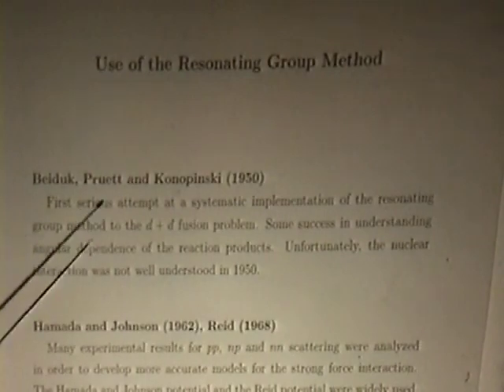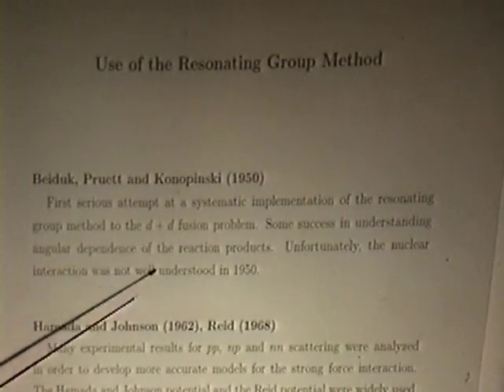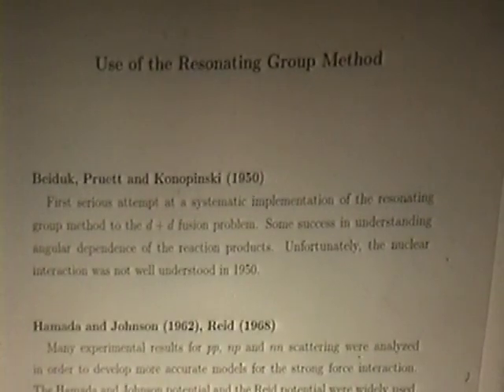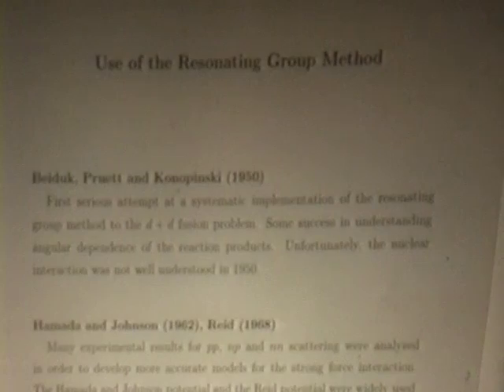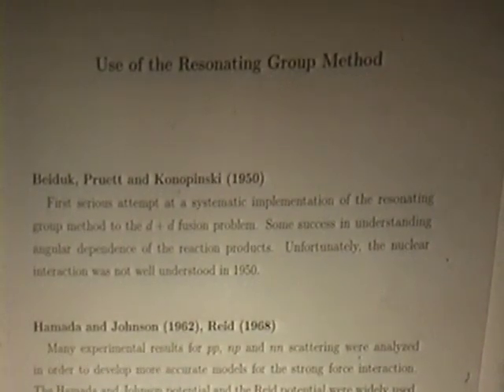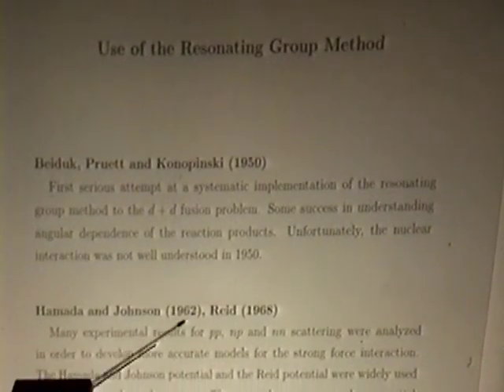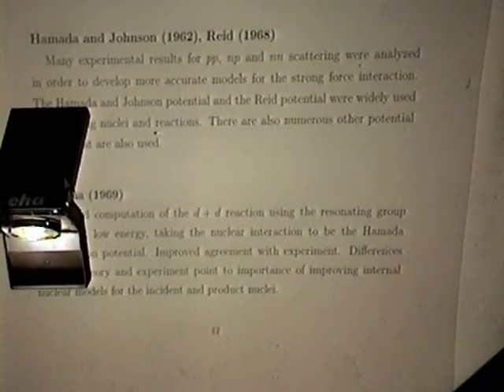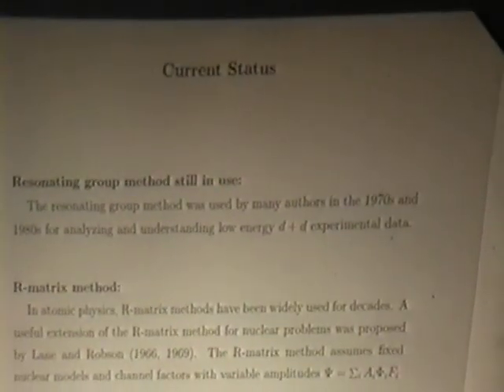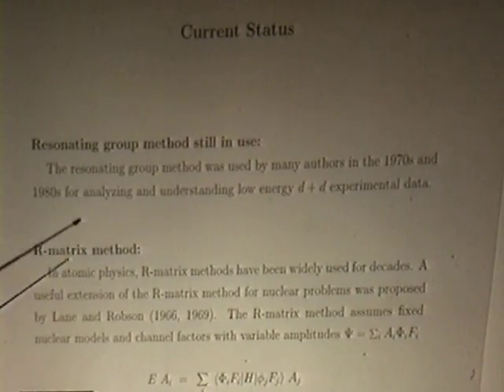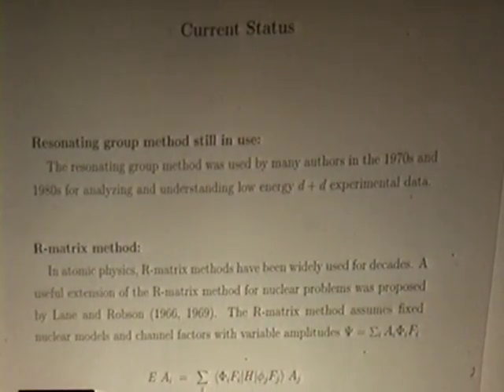You'd like it to at least reduce down to what normally happens. More papers used the resonating group method for the first serious calculation of the DD fusion cross-section. Unfortunately, back in those days, the strong force wasn't known particularly well. In the meantime, Hamada, Johnson, Reid, and other nuclear potentials were fitted up from scattering data. Boersma, in 1969, published the results of a PhD thesis where he used the good nuclear potentials as the basis for a resonating group method calculation of cross-section, and it greatly improved agreement between theory and experiment. Present status of all of this, which actually Jerry Hale talked to us about in Hawaii some years back: the resonating group method, in fact, is still in use. You find papers in the 1970s and 1980s published.